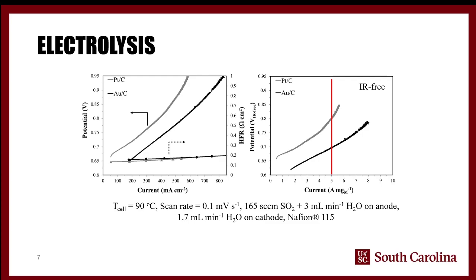We flowed 165 standard cubic centimeters of sulfur dioxide and 3 milliliters per minute of water on the anode, with 1.7 milliliters per minute of water on the cathode, and this was with the Nafion 115 membrane. So it's around 50 microns or so in thickness.